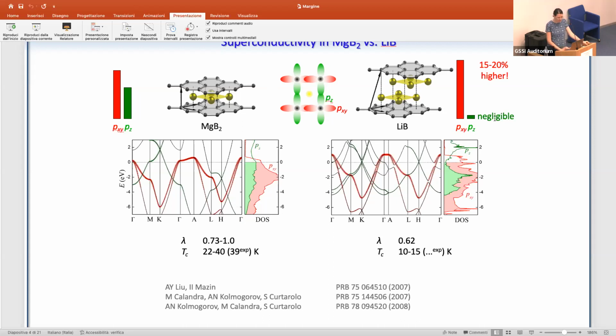On the other hand, in lithium boron, as you can see here, there is some density of states that comes from the lithium nearly free electron bands. This is reminiscent of what happens in calcium intercalated graphite. So despite these promising electronic features, it was estimated, based on the McMillan expression with the isotropic Eliashberg spectral function computed with Quantum ESPRESSO, that the Tc should fall between 10 and 15 Kelvin.